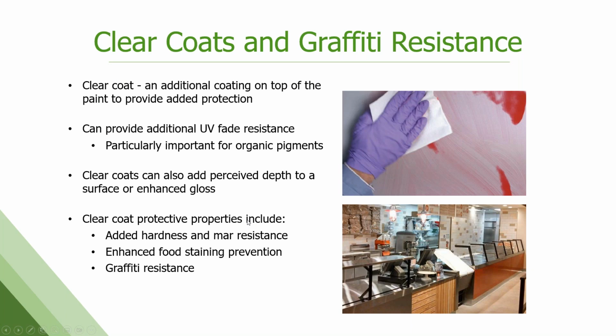Clear coats and graffiti. So we talked about clear coats adding protection in marine environments. They're basically like sunscreen. So there are actually kind of clear translucent UV blockers in these clear coats that help protect the coating underneath it. If you were to look at them by themselves, they actually have a slight yellow tint to them. Because of that, they're not completely translucent, 100% clear. So we use those over organic pigmentation when it's needed. It can also be used to add enhanced gloss, get you a little bit more perception of depth on the coating by using a clear coat.